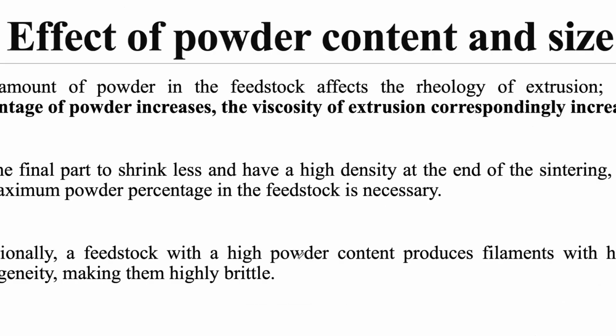Now, of course, there will be the effect of many things in this: what is the morphology of the powder, what is the size of the powder, what is the shape of the powder, how much powder you are using. All these things have some role to play in the picture. So, like I told you, read this third point. A feedstock with high powder content produces filament with high inhomogeneity, making them highly brittle. If there is a lot of powder and very little polymer that you have added, your filament will become very, very brittle. For the final part to shrink less and have a high density at the end of sintering, having the maximum powder percentage in the feedstock is necessary.